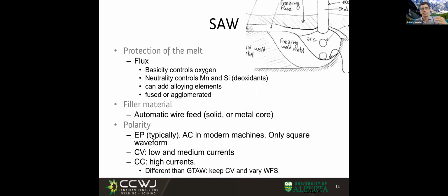And the wire feed speed will accommodate to whatever it needs to be that keeps the same voltage, which means same arc length, and the same current, which means same arc force, right? And the wire feed speed doesn't vary very much. When you look at data acquisition signals, you see how the wire feed speed varies a little bit higher, a little bit lower, a little bit higher, a little bit lower.